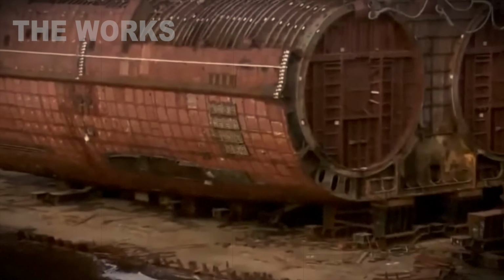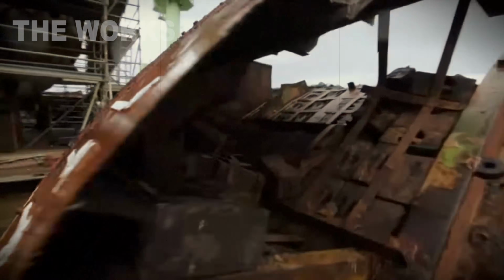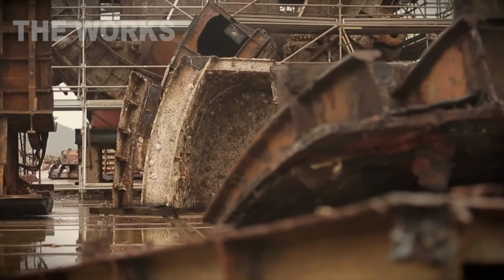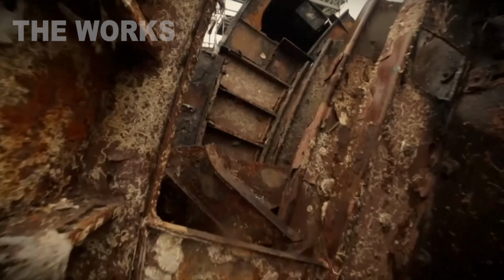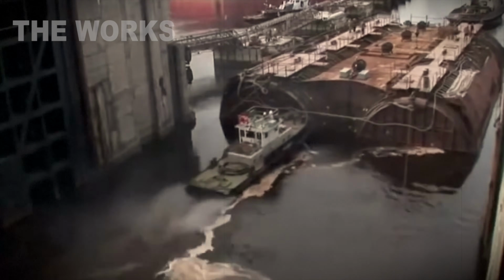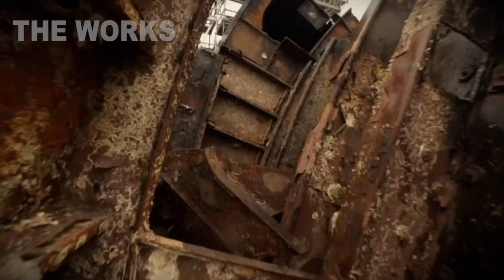Steel burns. Massive amounts of heat pour out. Temperature in the burn zone, 6,900 degrees Fahrenheit. The lance burns clean through the steel, leaves a molten seam 2 inches wide, burn through speed, 20 inches per minute, faster than plasma. But it takes serious skill.